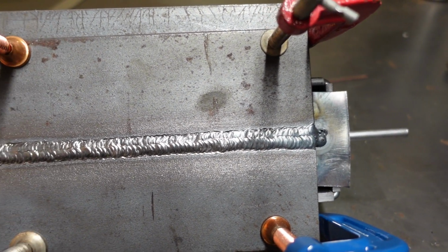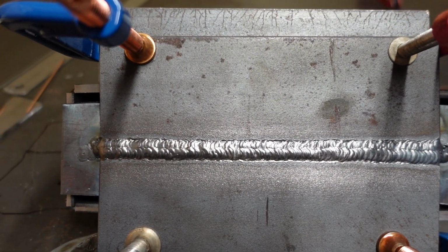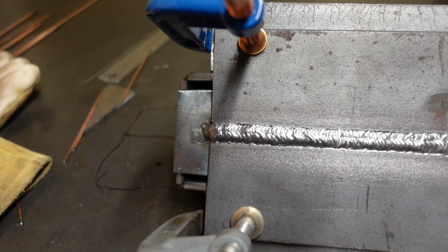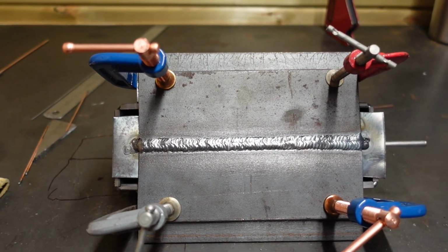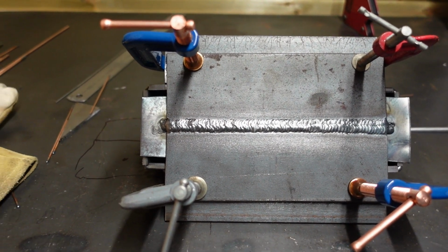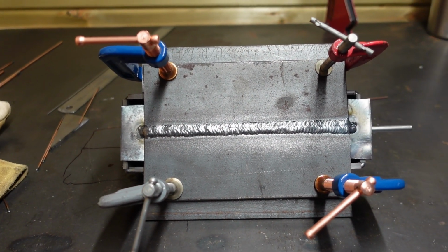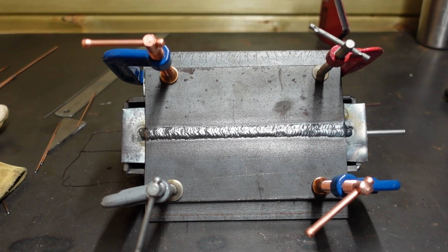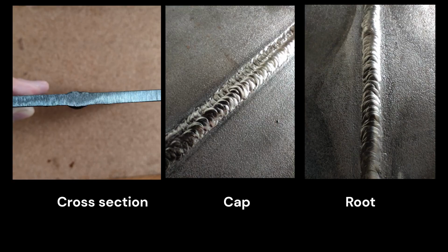Here she is, all capped, done and sorted. Now to let it cool down, because right now that's too hot to touch. Cut off the runoff plates, give it a final wire brush and tidy up, and see how we are. Here is the finished weld viewed from the root, a cross section and the cap. The root looks good, I'm happy with that. The cap, I'll acknowledge, is not my best. I should have added a little more amps to make it smoother. But I've got full penetration, a nice root, and I'd happily offer this up for an X-ray test and any other inspection test.